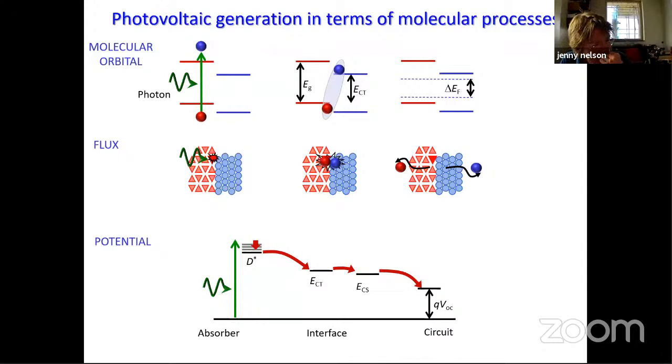I'm not sure that I find the easy way to answer that, because it's quite difficult to use the band structure concept for organic semiconductors, because we don't normally have periodicity. I would have said that when you have defects in the band gap, they would affect things when charge carrier density and mobility are low, and become less important when the charge carrier density becomes high, simply because you're not dependent on getting a charge carrier out of a trap in order to make a current flow. So that's the common view. There may of course be exceptions, but the more common finding with organic semiconductors is that mobility can increase with charge carrier density, and that has been assigned to the filling of traps.